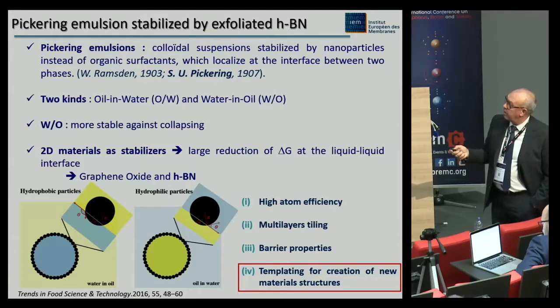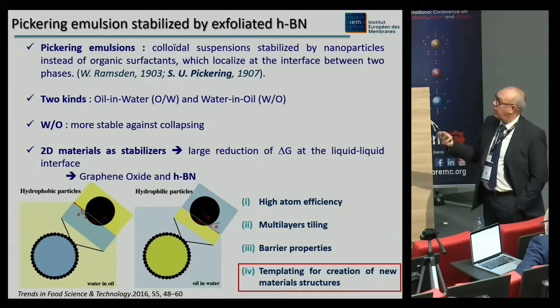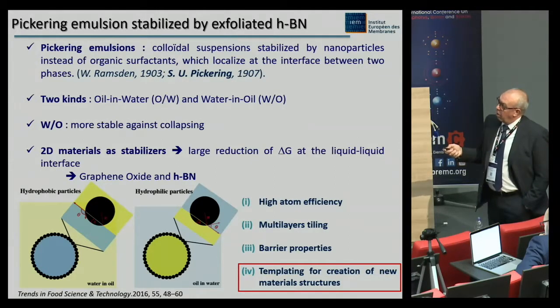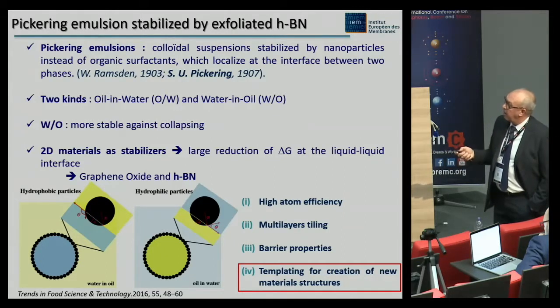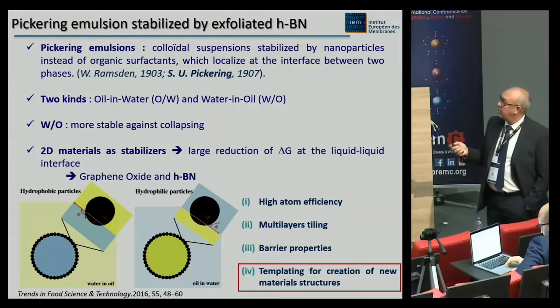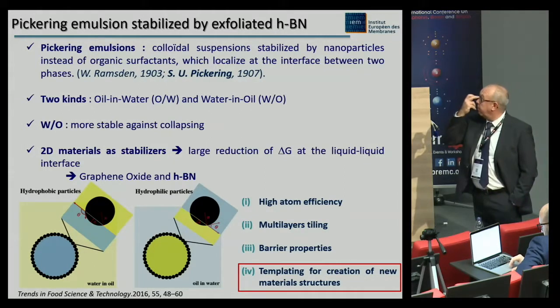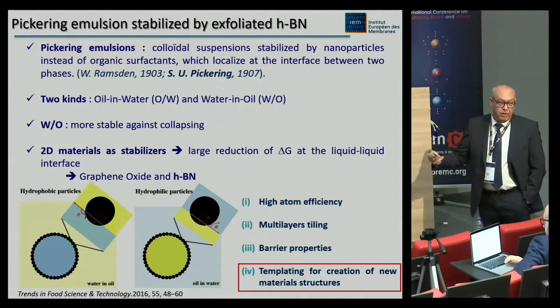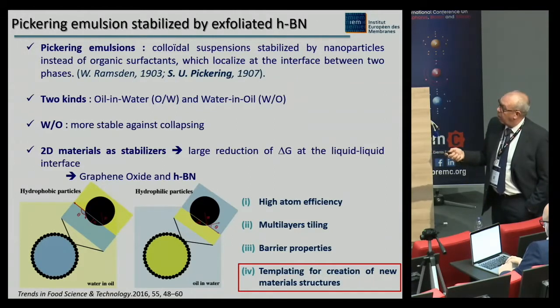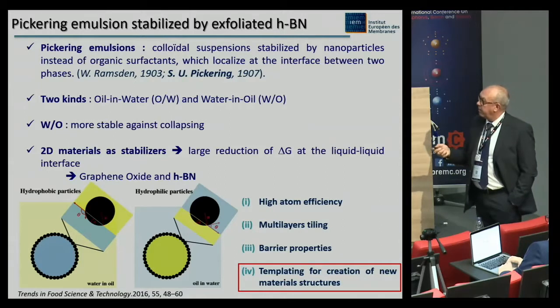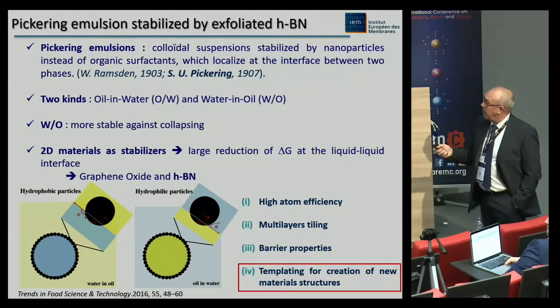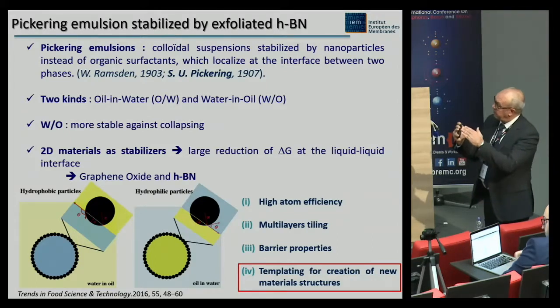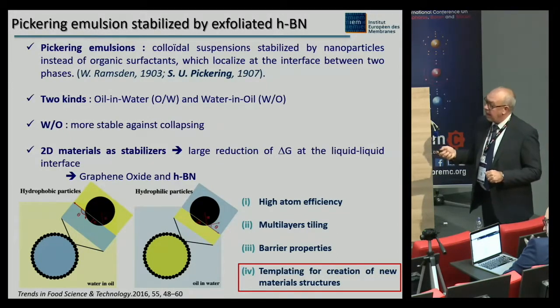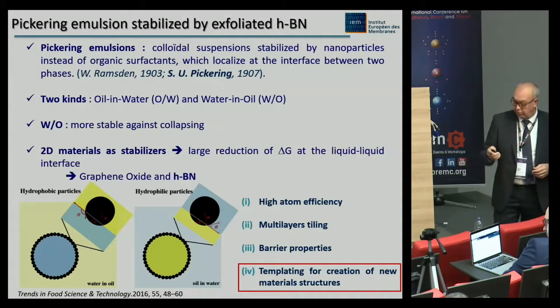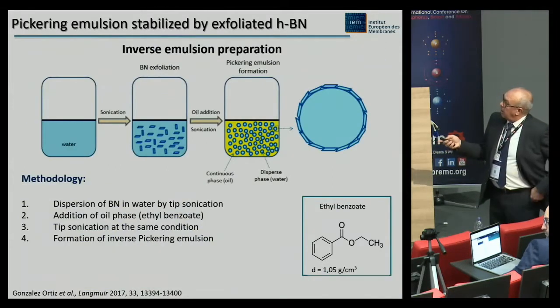Two kinds of emulsion exist: oil in water, meaning oil drops in water, and water in oil. Water-in-oil emulsions are the more stable against collapsing, and the interest of 2D materials as stabilizers is the large reduction of the free energy at the liquid-liquid interface, providing very good stability of the system. So we have worked on graphene oxide and particularly BN. The interest of this method is high atom efficiency, the multi-layer tiling which is possible with flat particles, the barrier properties at the interface, and also the templating for the creation of new material structures. So this has been done very easily.